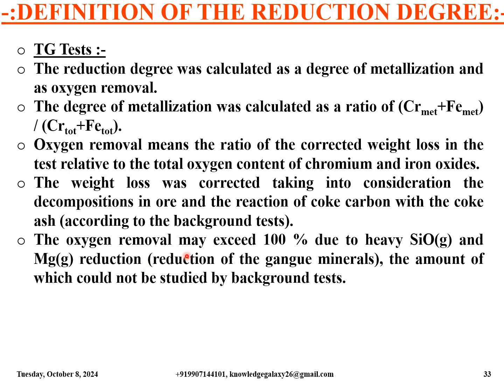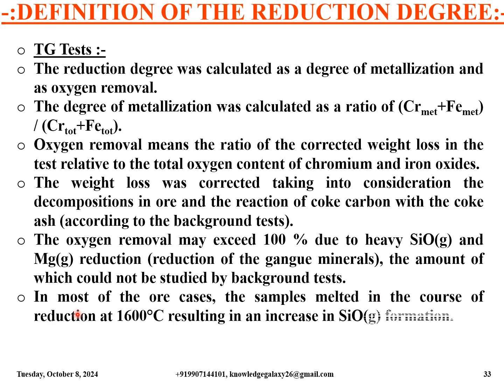The oxygen removal may exceed 100% due to heavy SiO gas and Mg gas reduction, reduction of the gangue minerals, the amount of which could not be studied by background tests. In most of the ore cases, the samples melted in the course of reduction at 1600 degrees Celsius, resulting in an increase in SiO gas formation.